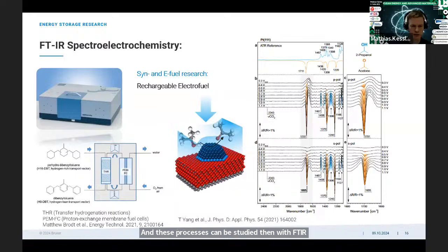So we can study the oxidation process in the fuel cell on the electrode surface. So again, platinum is used in this reaction, and then we see in the IR spectrum the bands which are going down in this case are then the product which is created, and the bands which are going up in the spectrum, this is the educt, so 2-propanol, which is consumed. And then we can also use the polarization for the measurement and increase then our sensitivity on the surface. And if we use P polarization, you see here the intensity of our absorption bands is much bigger. So also for fuel cell research, spectroelectrochemistry is a very useful tool.